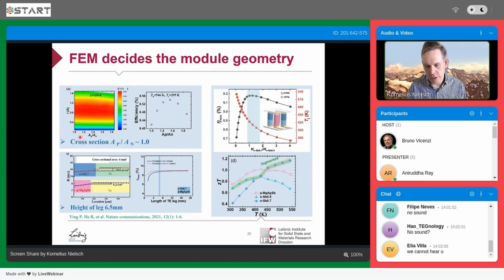We also measured, for example, the contact resistance. This is very promising for the P-type material, where we have the contact with silver, and we have a slightly elevated contact resistance when we have the iron. Overall, it leads to a very promising efficiency. The prediction from the first finite element simulations was about 9%.